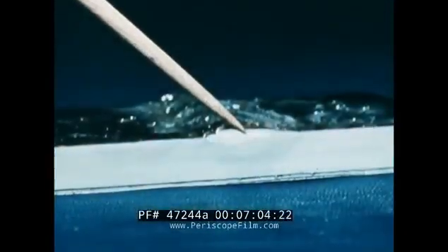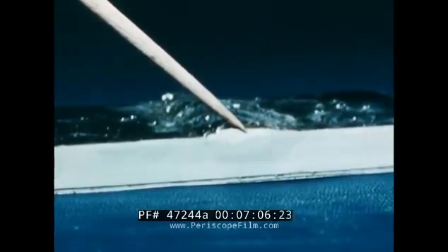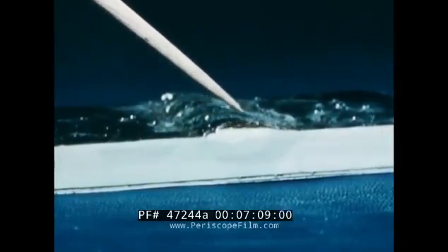The weld metal is left on top of the plate with poor fusion between the base and the deposited metal. There might be some slag inclusions. If the arc is too short, a proper molten pool will not be maintained. There will be gas and slag inclusions.